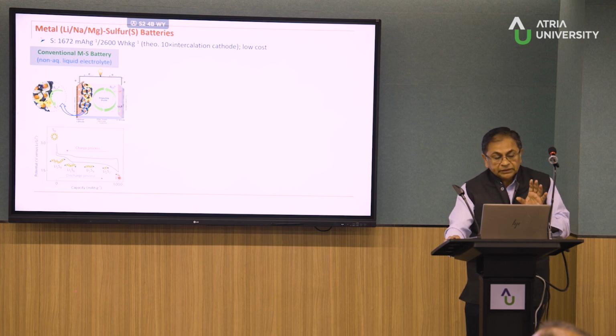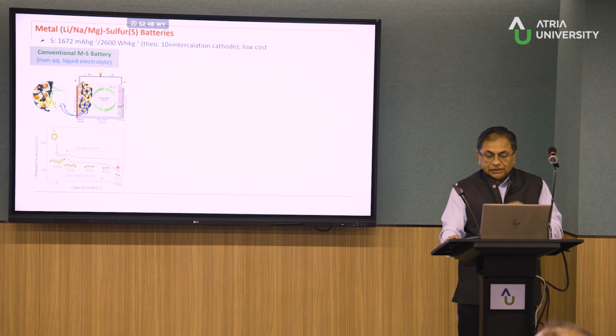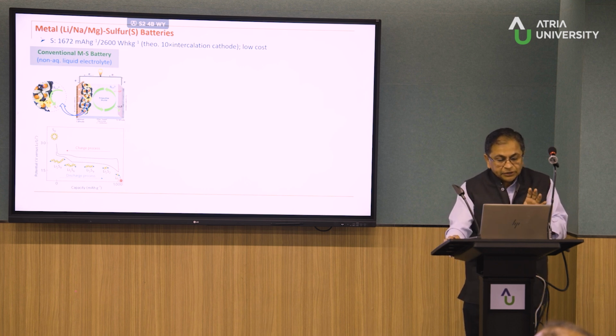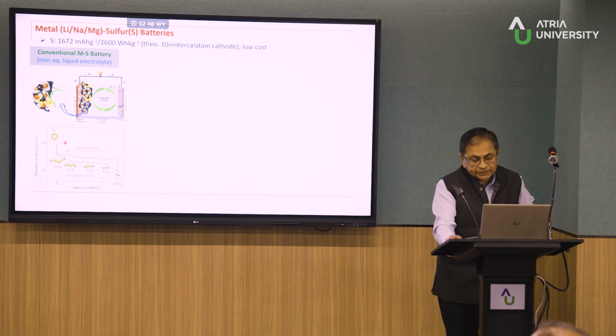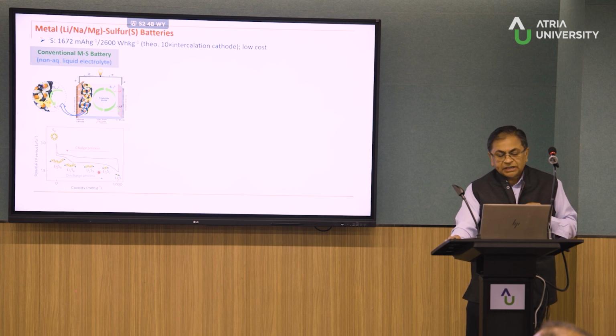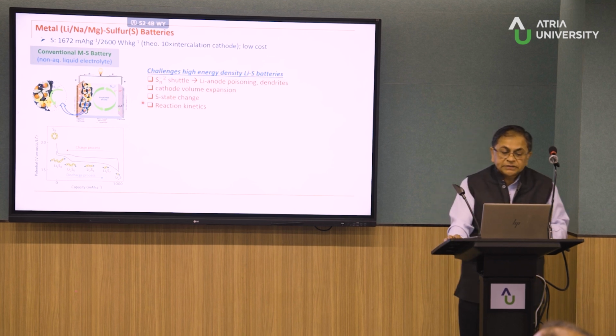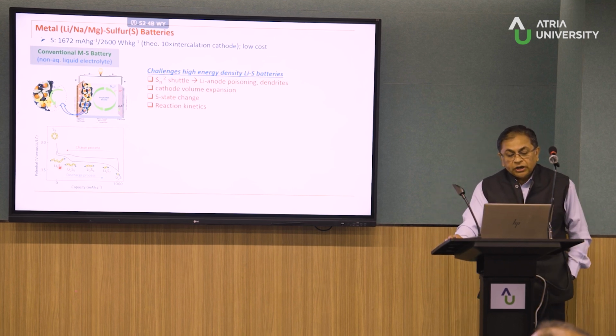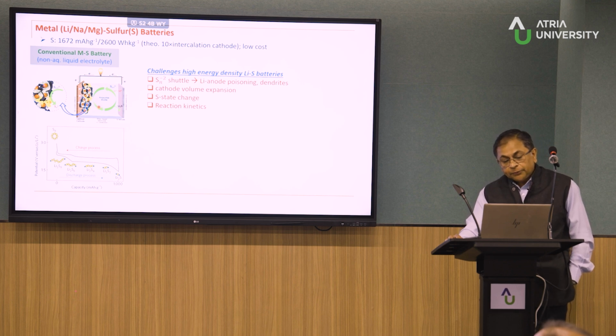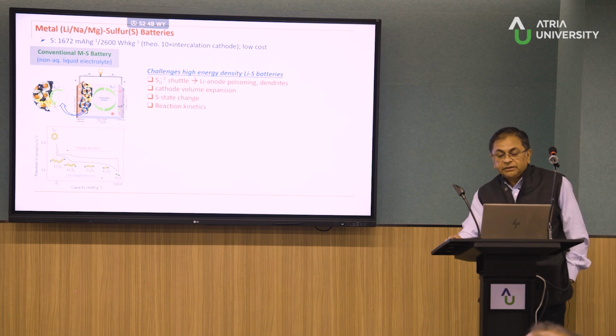So it may appear to be a very simple cell giving high energy, but the operation of the cell is quite complex. And then when it charges back, to S8. So as you see, this is multi-step, and the major problem of the sulfur system is this redox shuttle. If the polysulfide dissolves out of the cathode, it has a tendency to diffuse towards the anode side, and it starts poisoning the anode. It forms the end product on the anode side. So you have a problem of loss of sulfur, and a problem of capacity fade just from this.